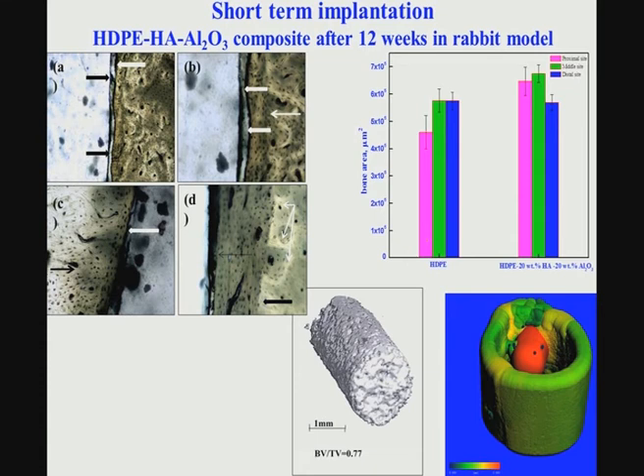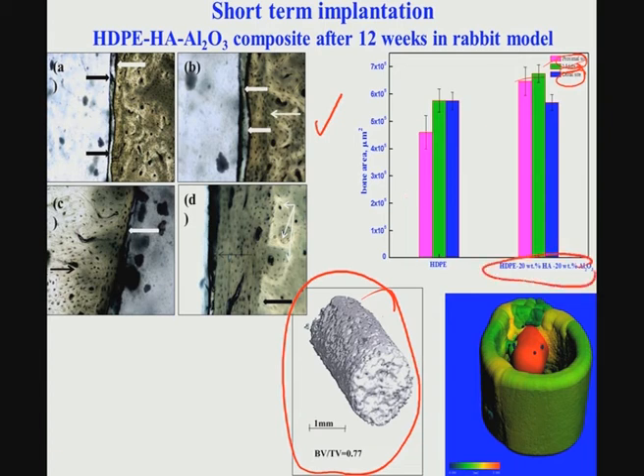Now, in the short term implantation we have done some microCT analysis also, and it shows the bone volume to total volume. We have also done histology images to see the typical bone area of these materials, and the bone area in the distal side, the middle side, and the proximal side. So, normally what you see is that with the high density polyethylene hydroxyapatite alumina composite, not only is your osseointegration uncompromised, but also quantitatively the bone contact area increases. That means this material promotes more and more bone regeneration around this implant.